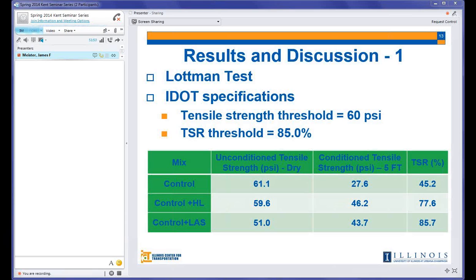The addition of lime really contradicts here with what is mentioned in the literature. It is well known that lime usually increases the stiffness or the strength of the mix. Here, 1% was not enough to make any significant alteration. It's 59.6, very close to the threshold. While the addition of liquid antistrip dropped the tensile strength compared to the control, which agrees with the literature, because liquid antistrip is believed to soften the mix, reducing the strength or the stiffness of the asphalt mix.